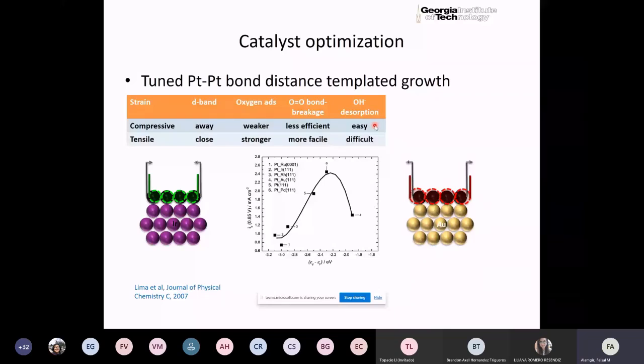They're not the same effect. So you can essentially get a compression can induce a weaker adsorption and less efficient bond breakage. However, it can make it easy for the desorption to take place, so that you don't get a poisoning of the surface. However, if you have a tensile strain, you have a stronger adsorption, which may end up being a weak link if it's too strongly bonded. But when you adsorb this oxygen, it also makes it more facile, more easy to break the oxygen-oxygen bond, which means that as you adsorb, you immediately would be breaking the bond, which would mean that you could move to the next step. The next step would then be the desorption of the OH, and in this case, it is a little more difficult. So neither of these two on their own is optimal, and that's where the electronic effect can play a role. So you can see here the effect of the different types of substrate material on platinum.